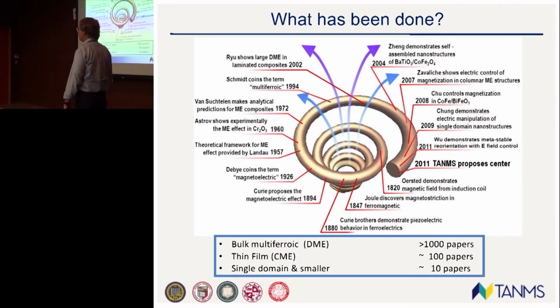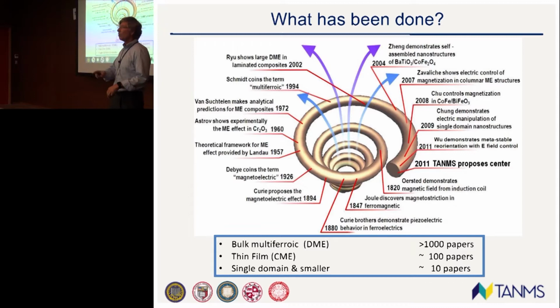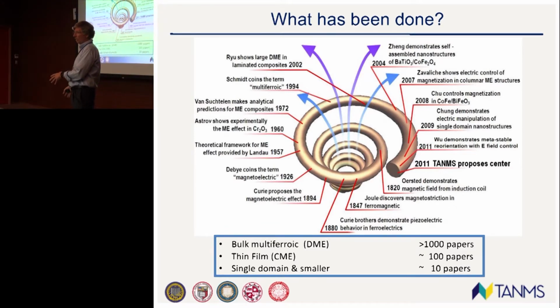Now I'll go down into thin film, and I'm only focusing on strain-mediated, where you're applying electric field controlling magnetism. Yeah, there's a few out there, hundreds. But now if you go down to single domain, get rid of those domain walls, and you're actually going to try applying electric field and actually control the magnetic state, there's only a handful of papers. So if you really want to make your mark as far as writing a great paper, this is a great area to work in. But I'm going to try to convince you it's more than just writing a great paper. You actually have the potential to do something revolutionary for society. It makes a really big impact if you can actually get that efficiency number up there.